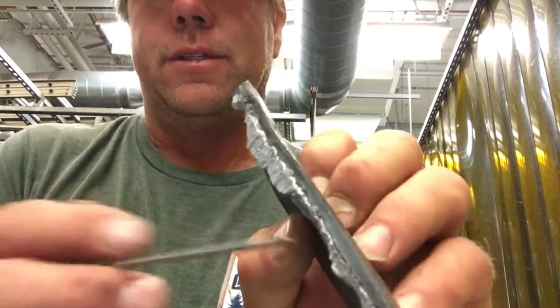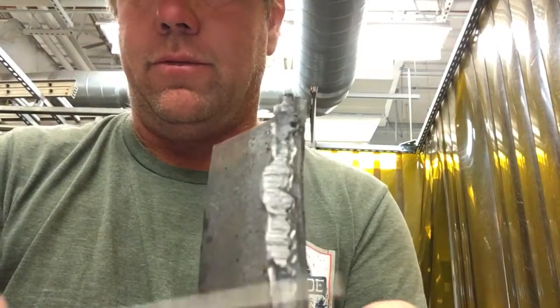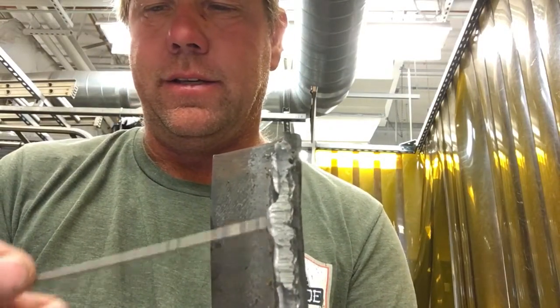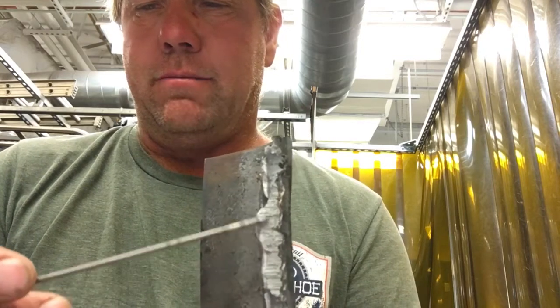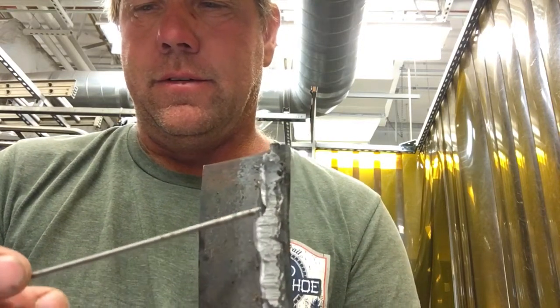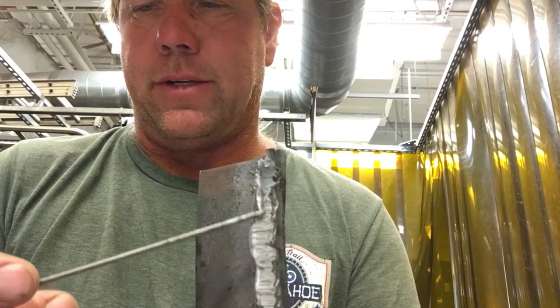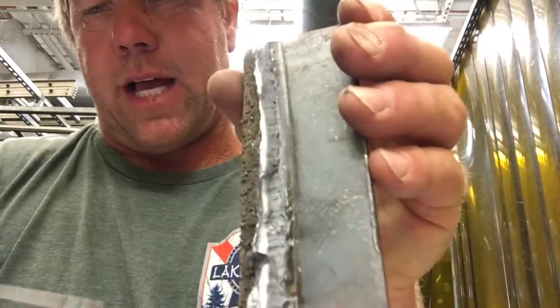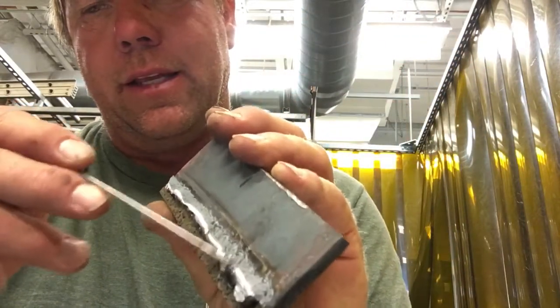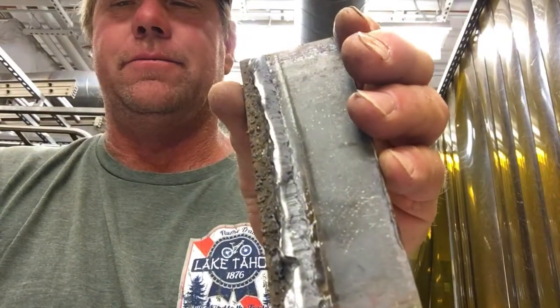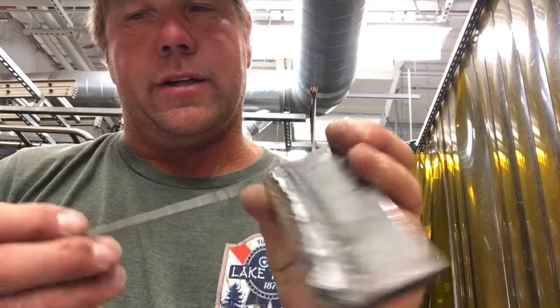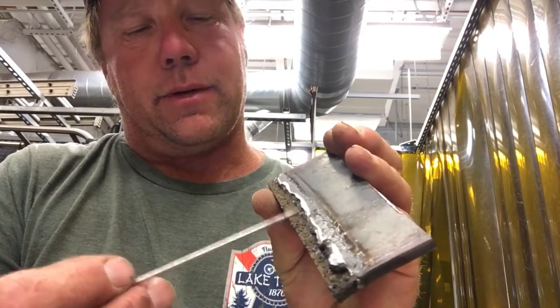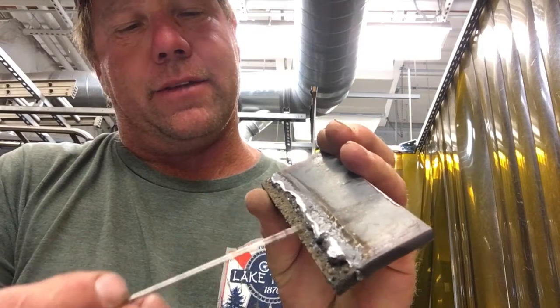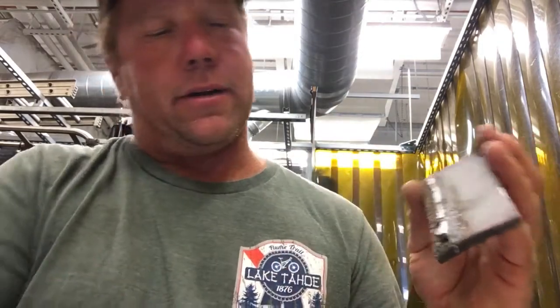Let's look at some defects that are maybe interesting to see. So first off, let's look at this. You see that real woody kind of grain? That is actually beyond the heat affected zone, and now I'm starting to rip up the base material. That's actually the base material. And you can see that right here where it's actually coming up out of the base below the plane on that outside edge of the heat affected zone. These little balls right here, since it's a triple pass done with 6013, 125 amps, this would be spatter. That's another defect. So far, slag pocket, spatter, arc blow.